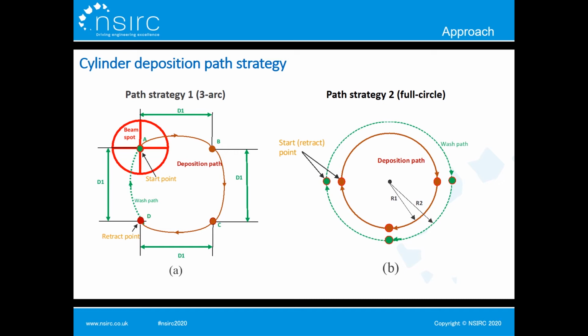Then based on the 3-arc experimental results, after improvements on the wire feed and retract points in order to fix the angle issue, on the right-hand side a full circle path strategy was developed, which has a full circular deposition path to feed the wire and an extra wash path to let the laser scan the deposition so that it becomes flatter. The following slides will show the results of single and multiple layer depositions applied by these 2 strategies, both in geometrical and macrostructural aspects.